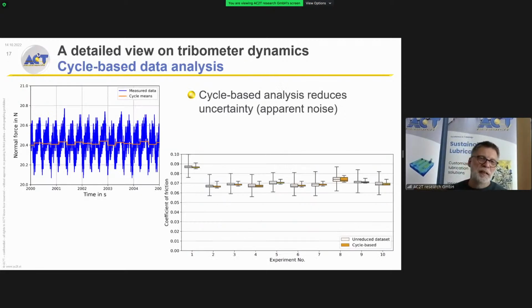Another important aspect is that you should evaluate the data on a cycle-based analysis. That means take one cycle after the other, look at what are the periodic features and what are the non-periodic features, and then you can reduce the error bars or the uncertainty of your data to a great amount. And this will give you, for any later data analysis step, much more reliable and clean data, I would say. So that's what you can see on the right graph here.